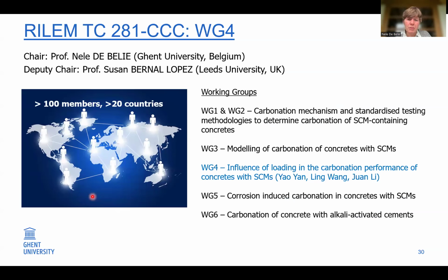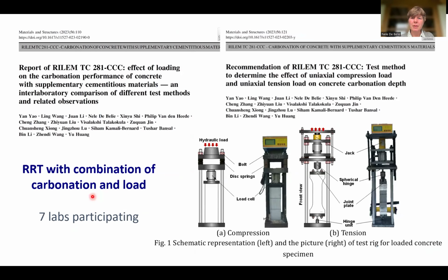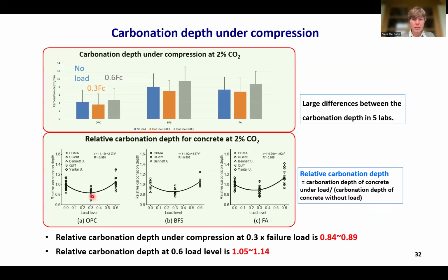Working group 4 carried out an additional interlab test to study the combined action of carbonation and mechanical loading, and they also made a recommendation that can be consulted in Materials and Structures. The results indicated that the carbonation depth is lower in the case of a limited compressive load, like 30% of the failure load, and that is actually because of compaction. Whereas if the load is increased to 60% of the failure load, there is also an increase of carbonation rate because some damage and micro cracks start to occur.